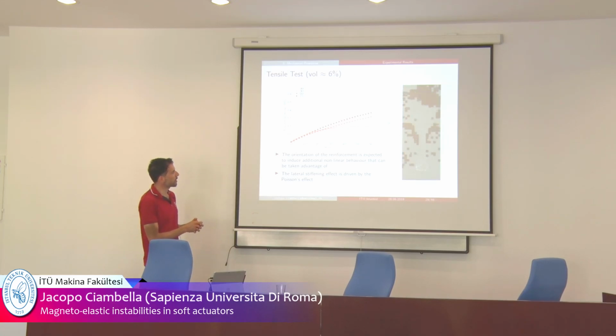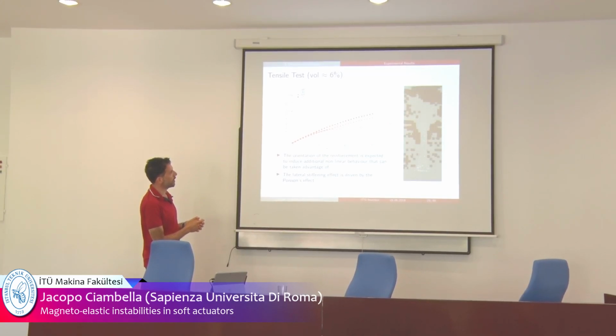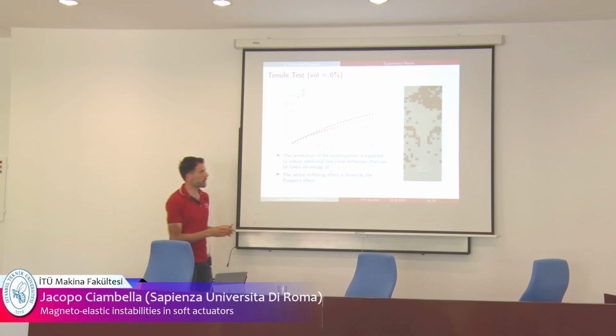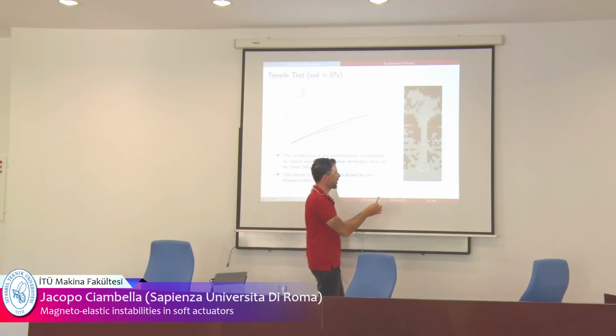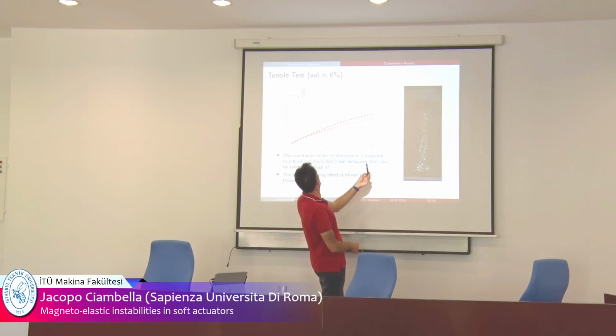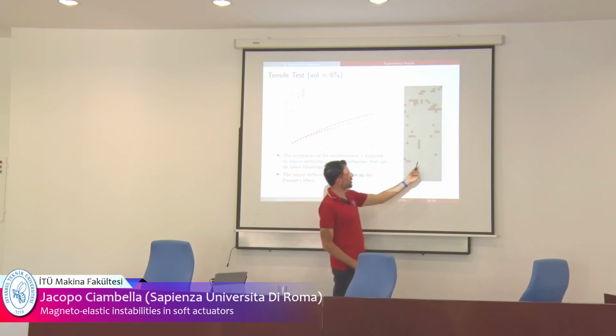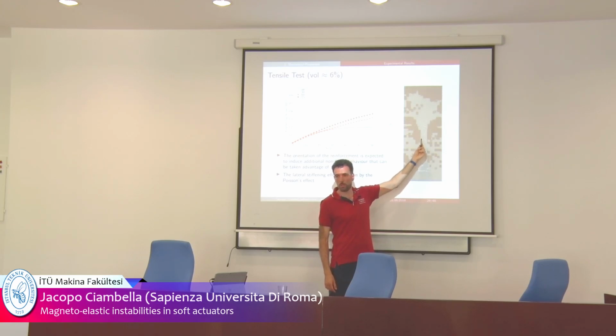And these are the effects of the orientation: 0, 30, 60, and 75 degrees. As expected, you have an increase of the Young modulus when the fibers are oriented. But you should notice that the fibers at 75 degrees are somehow weaker than the 30 degree ones. Okay? So 0 degree means that the fibers are in the direction of the load, sorry.